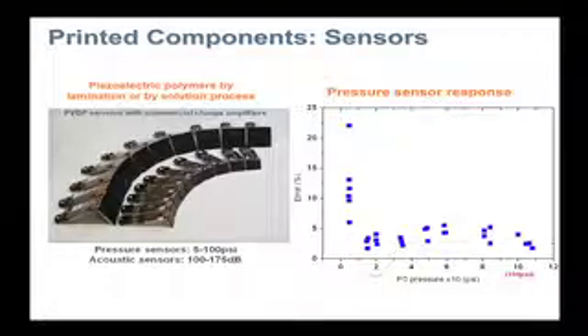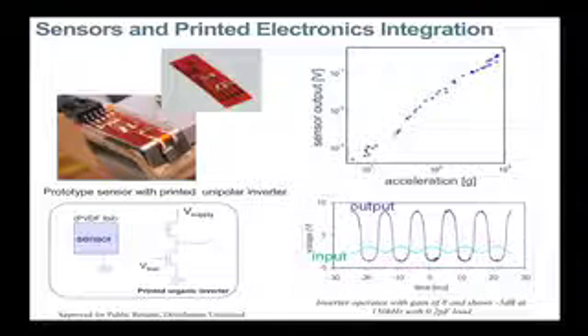The trend is the important thing here because the actual values will depend on the geometry of the sensor. How well did they work? They were actually quite good. You can see here, this is going from pressures from 10 to 100 psi. So for very low pressures, we had high error. But from 10 to 100, the accuracy of the sensor was around 2.53%. So if you think about that, one sensor can give you measurements from 10 psi to 100 psi, that's really good. It was a good proof of the feasibility of the technology.